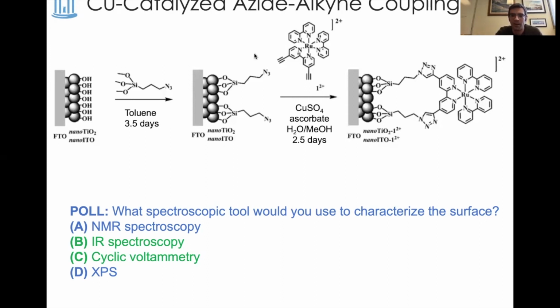So there usually was a little bit of azide left over, just based on the amount of ruthenium that we could pack. These are a lot bigger molecules than these azidosilane units. So we think that sterically, not all of the azides were chemically accessible. Cyclic voltammetry is also super useful after we got to the product, because this has well-defined redox events that you can use to learn how much ruthenium is on the surface, for example.